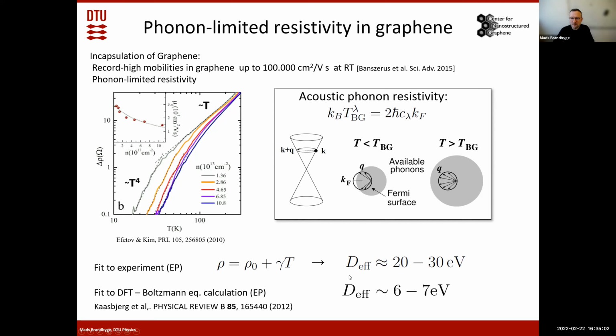And this deformation potential, if we compare it to state-of-the-art DFT calculations and the Boltzmann equation with the relaxation time, is actually maybe a factor of 4 or 5 bigger from the experiments than what you get from the calculations. So that means that in the calculations, you would get maybe a factor of 4 or 5 higher mobility than what you actually see in the experiments.